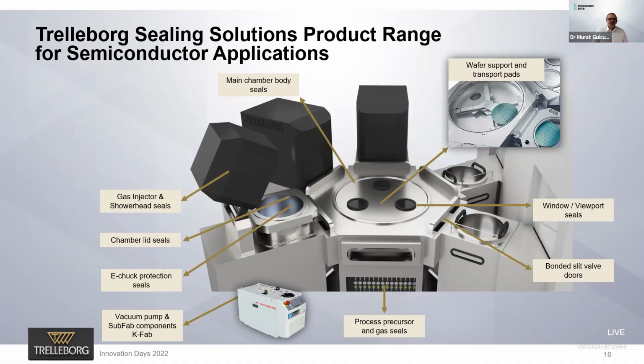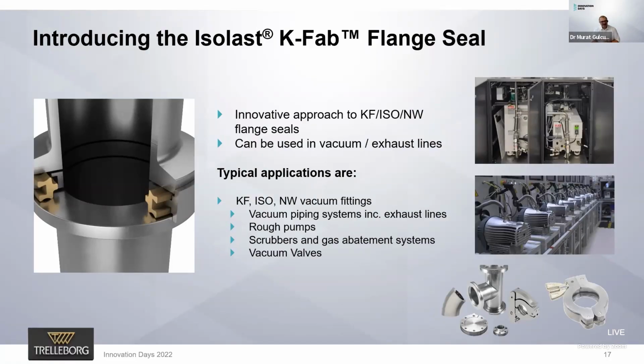And on top of these, we can also, of course, provide subfab vacuum pump and subfab components. I'm going to talk about our KFab seals in a moment, actually right now. So KFab flange seal. We have launched this product just a couple of months ago. KFab flange seal can be used in vacuum or exhaust lines, and they fit onto all KF or NW type of flanges, where normally centering rings are used between two metal rings. So Isolast KFab can be used on exactly the same, because it fits on the standard groove, standard flanges. So KFab seals can be used in vacuum piping systems, exhaust lines, rough pumps, abatement systems, vacuum valves as well. So they have quite a wide range of applications in subfab applications in semiconductors.